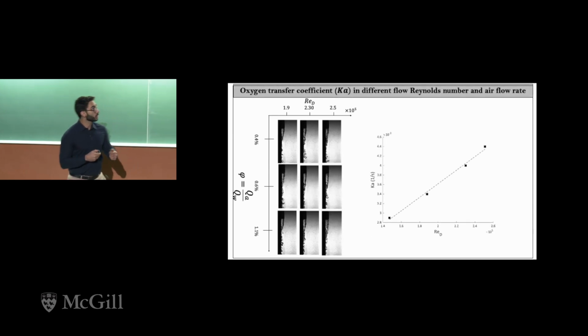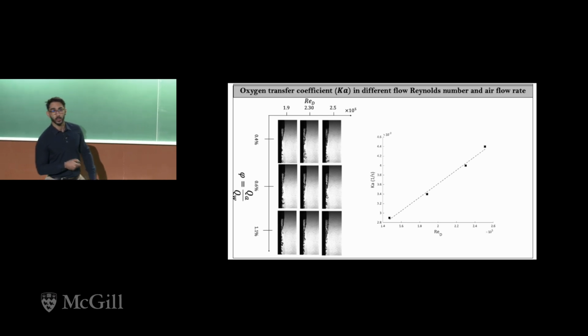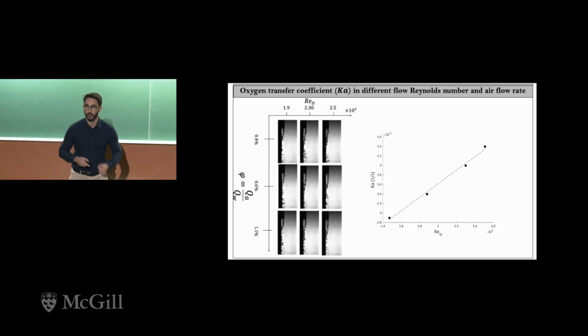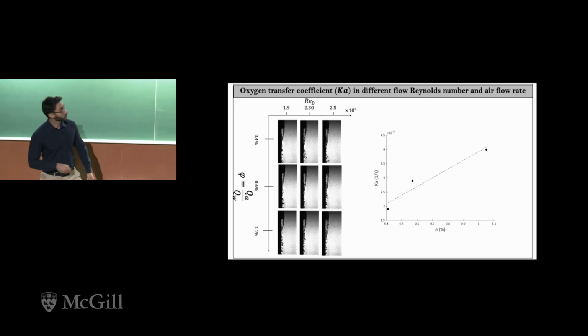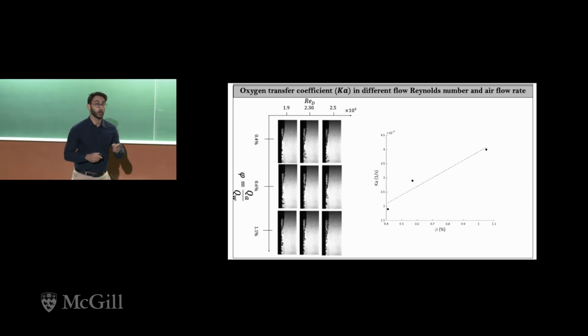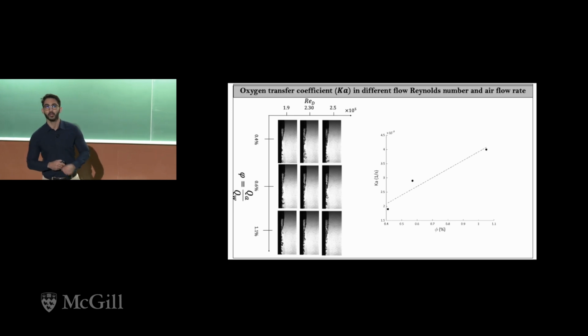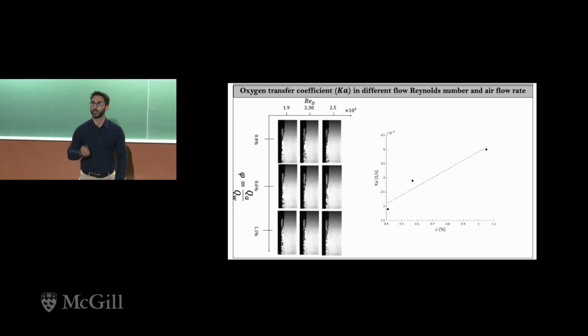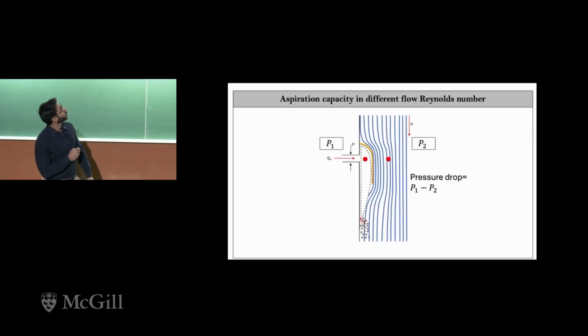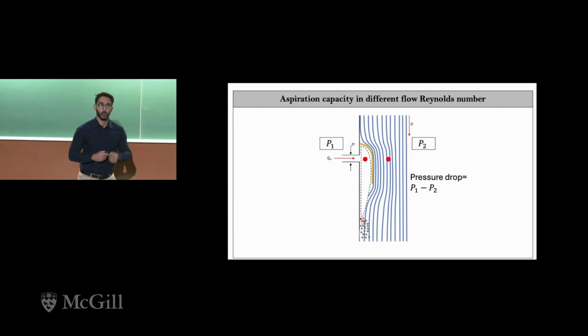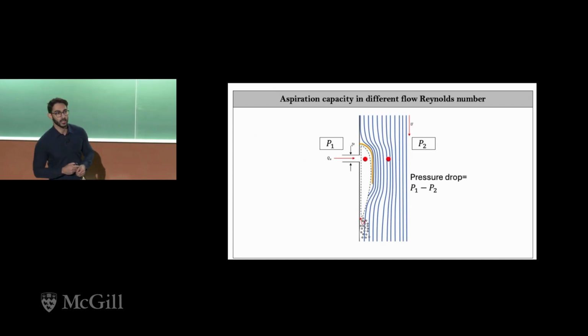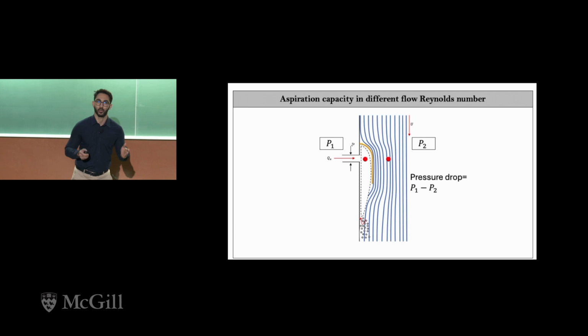And the results clearly show that by increasing the water speed, we have higher oxygen transfer rate due to the smaller bubbles, which is exactly what we expected. And also by increasing the air mass flow rate, we have an increase in the oxygen transfer rate as well. The other parameter that is important for us is the pressure drop across the deflector.